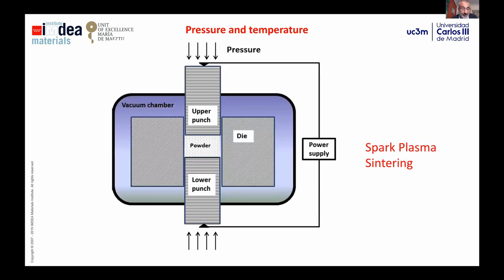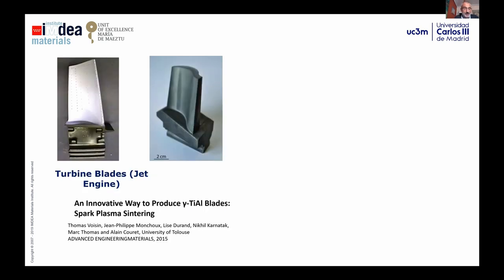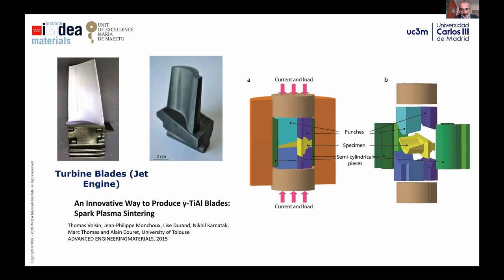But one of the negative things of spark plasma sintering is that usually the shape is just a cylinder, a blank that should be machined later in order to get the parts. But recently there is some work in which, thanks to computational modeling of the whole process, you can develop dies and punches that optimize the current passing through the powder, and you can get directly the shape of a turbine blade, and directly obtain the final part by spark plasma sintering. So this could reduce the price of this methodology a lot.